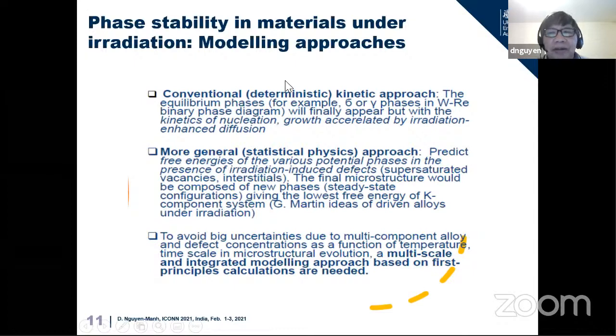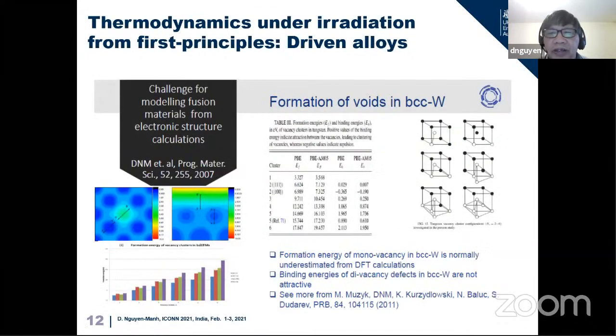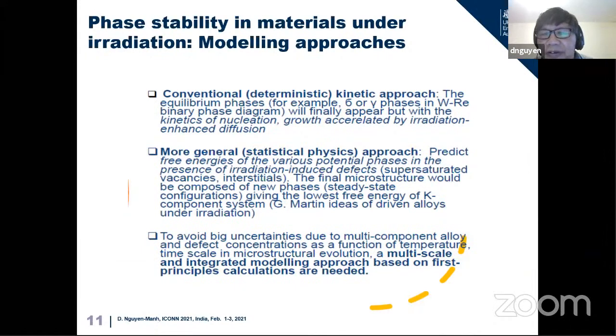So if you can build up the free energy approach and minimize the free energy, including the defect, then you can predict different phases, including the anomalous precipitation that we saw in the previous slide. That is the approach that we call thermodynamics under irradiation, which is not so new. It comes from Jacques Martin early on, on driven alloys, which considers alloys under irradiation and their changing properties. But at that time, with our initial calculation, it is quite difficult to see what we can predict realistically.